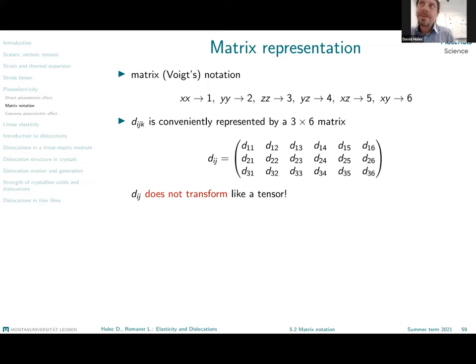The downside of this is that while we know how to transform the stress tensor, the strain tensor, or how to transform the piezoelectric tensor with three indices, we do not know a priori how to transform this three by six matrix from one coordinate system to another coordinate system. So if I want to express it in a different coordinate system, the way to go is that you restore your real physical object the tensor, which is a three-dimensional matrix. Here you will transform that from one coordinate system to another one by this three times multiplication of the transformation matrix and then again represent it by this three by six Voigt matrix.